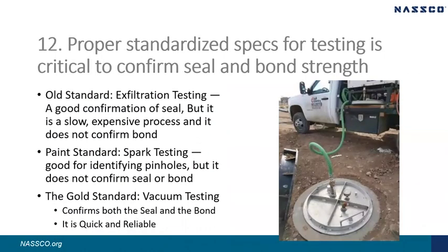Point 12. Proper standardized testing on the seal of a manhole is important. The old exfiltration standard, where one seals the pipe penetrations, then fills the manhole up with water, provides a good confirmation of seal, but it is slow and expensive, and it does not give a qualitative confirmation of bond. The paint standard spark test is critically useful for level C rehab coatings to identify problem pinholes in thin coatings, but it does not confirm seal or bond.